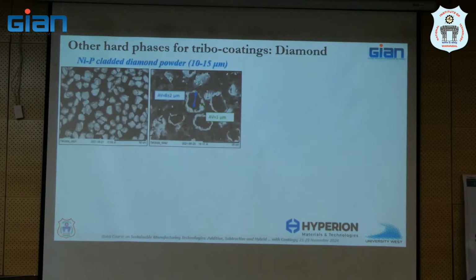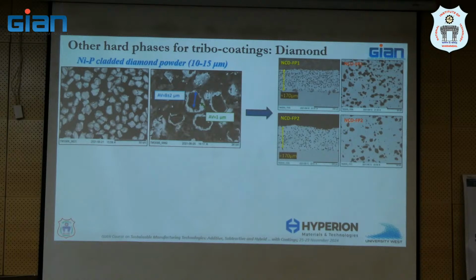Yeah, but that's what they do. So I said, I won't pay for it, but if you give it to me for free, I would love to spray these nickel-capped CBN and nickel-capped diamond. So that's how it started. We got some powder from them. This is nickel-capped diamond. We did some SEM. So each diamond particle is coated with nickel phosphorus, right? It's cladded like that. And we sprayed that. Amazing, right? When you looked at the microstructure, I wasn't sure if we would get a coating, but we did.